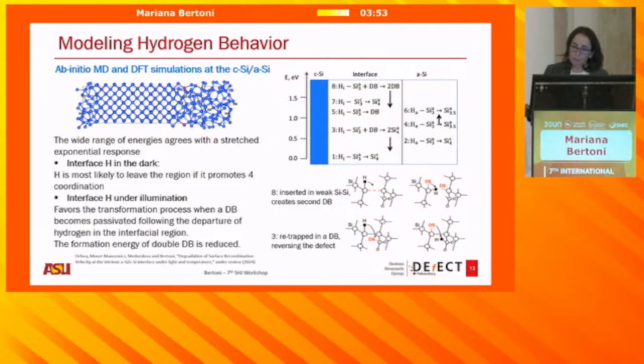So the next thing that we did was to ask our modeling collaborators to take a look at what are the transformations, what is actually happening at this particular interface. The first thing is that there are several reactions taking place. So here's your crystalline silicon, here's your interface, here is your amorphous silicon. And from all of these reactions, several of them have a pretty low formation energy.